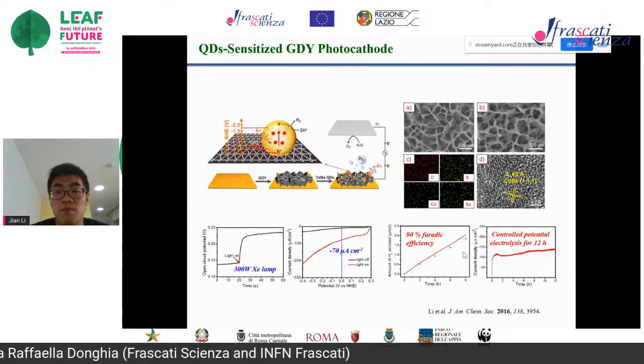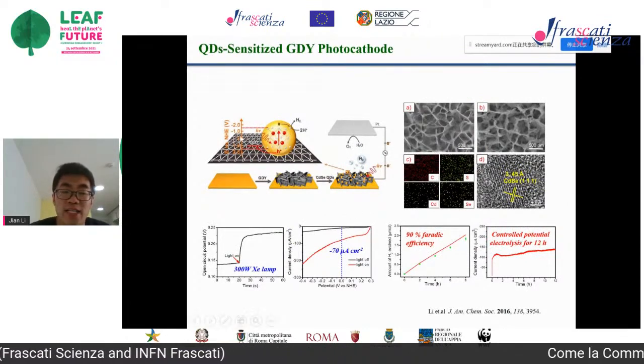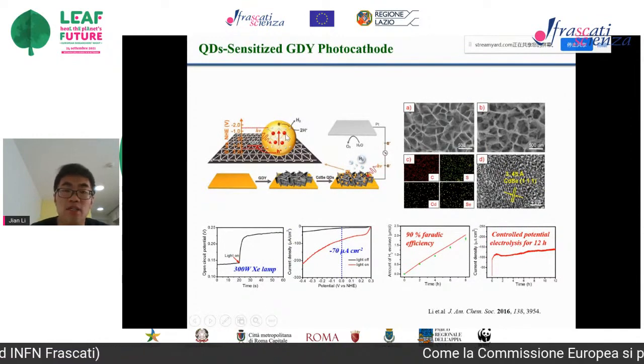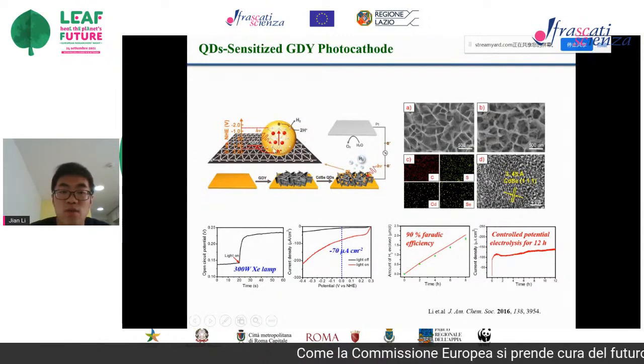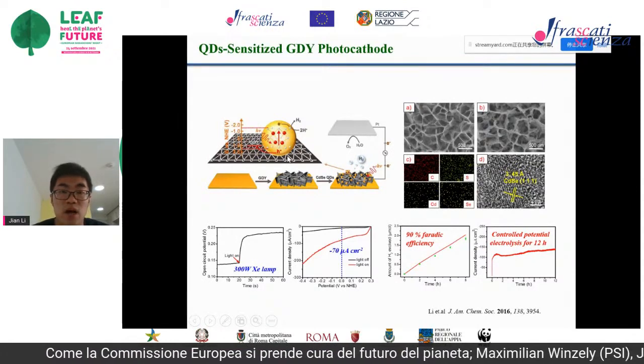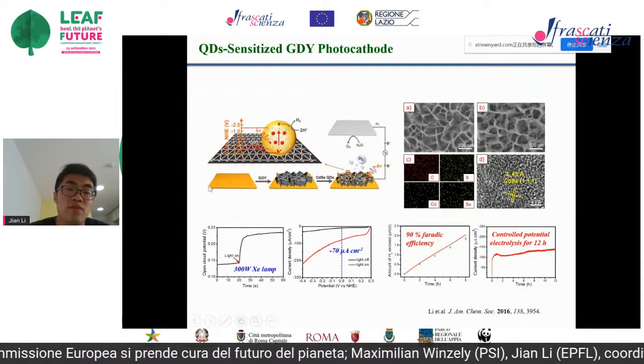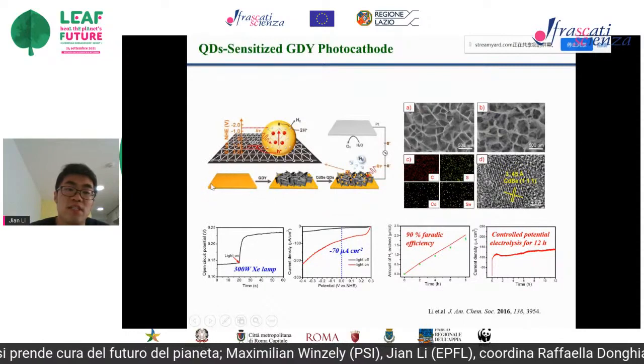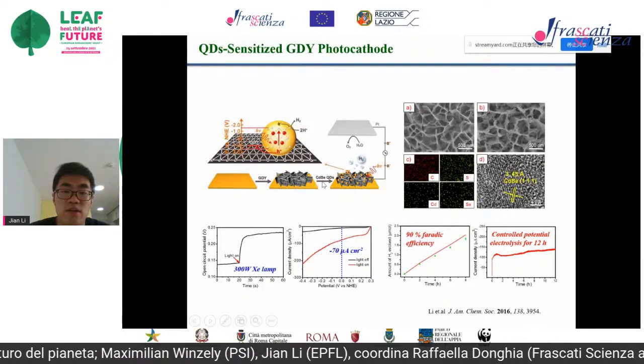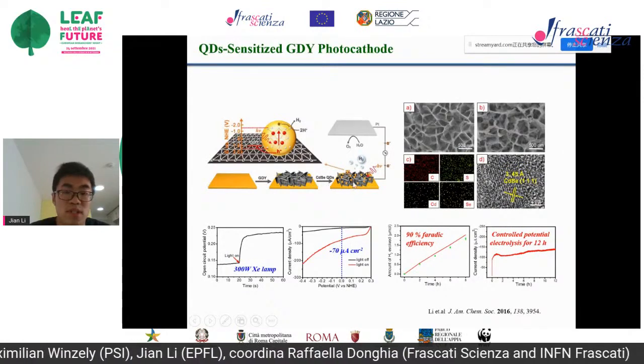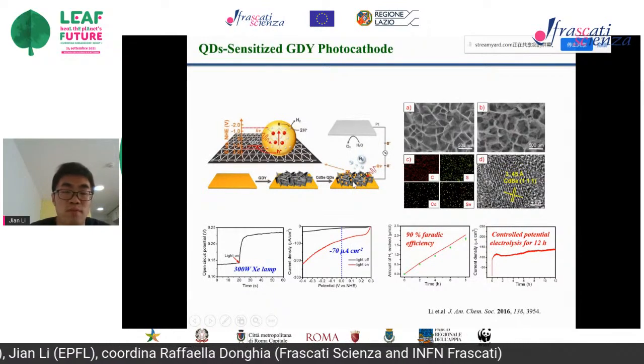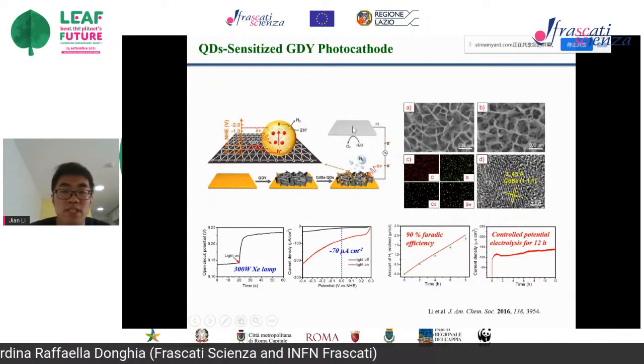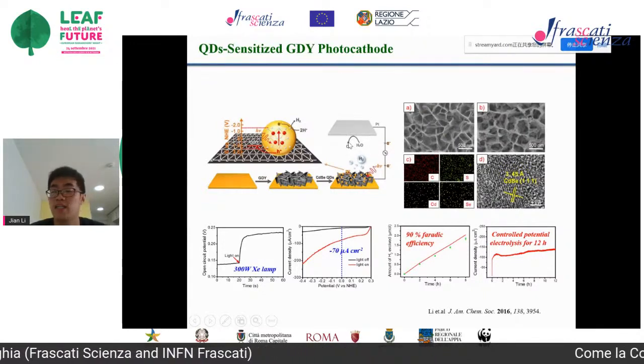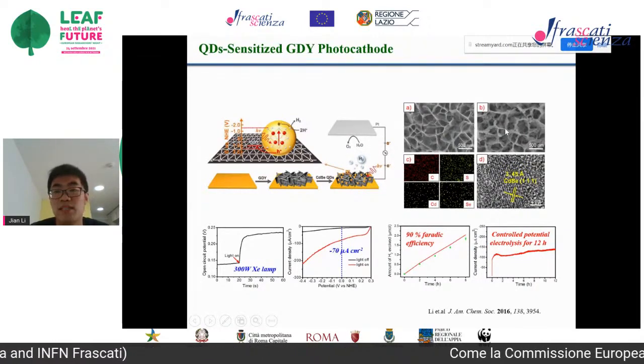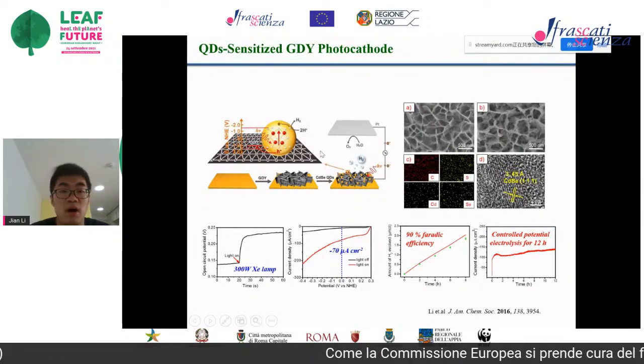We talked before that graphdiyne has very excellent hole mobility. So if we combine these quantum dots and graphdiyne, we can improve the overall efficiency. Here, we first synthesize graphdiyne on copper foil, and then we assemble the quantum dots on the graphdiyne film, and then we assemble the PEC cell to test the activity. And these are some SEM and TEM images of our graphdiyne.